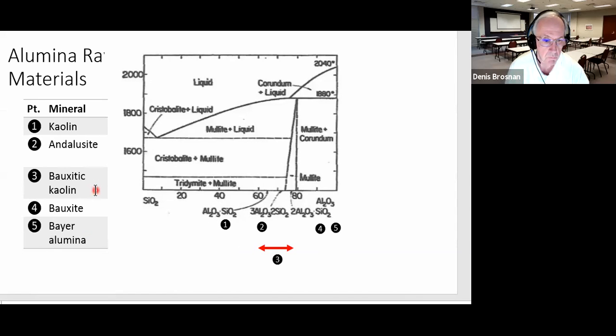Now, just as a little background, if you want to make something that contains alumina, well, you're going to start out with kaolin at about 40%, but if you want to make more alumina content in the fired product than that, then you're going to go to something else. Like number 2 is andalusite. That's a natural mineral that's imported into the United States. And naturally it's 60% alumina. But if you want more alumina than that, you might go to a bauxitic kaolin, which can get you up to about 70% alumina or thereabouts. That's the raw material available.